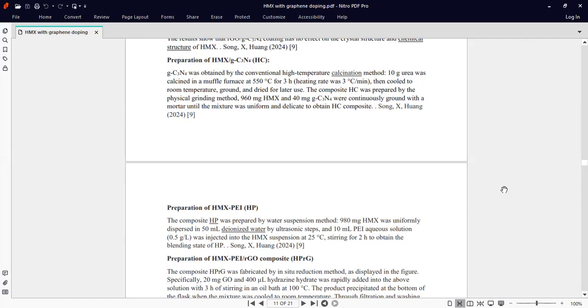The composite HC was prepared by the physical grinding method. 960 milligram HMX and 40 milligram g-C3N4 were continuously ground with a mortar until the mixture was uniform and delicate to obtain HC composites.